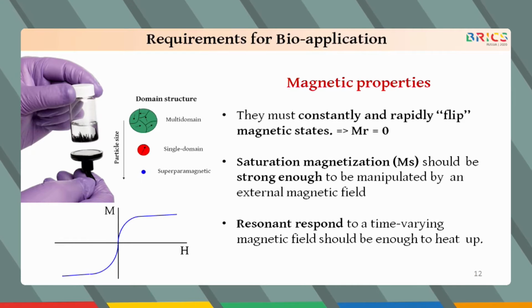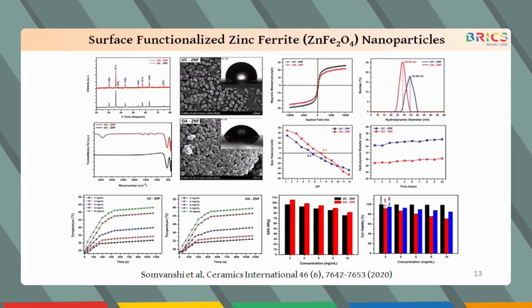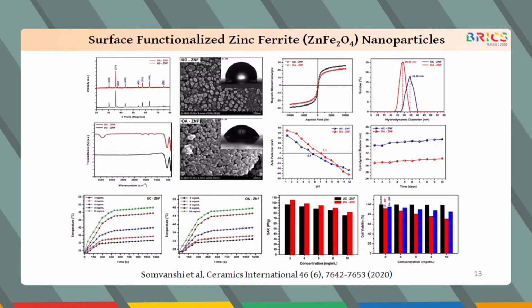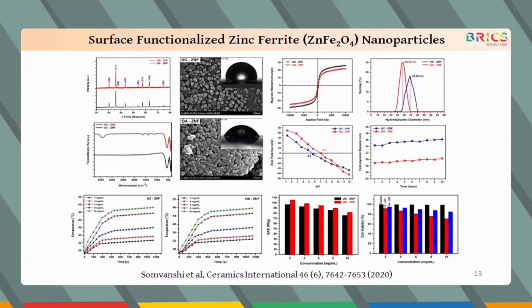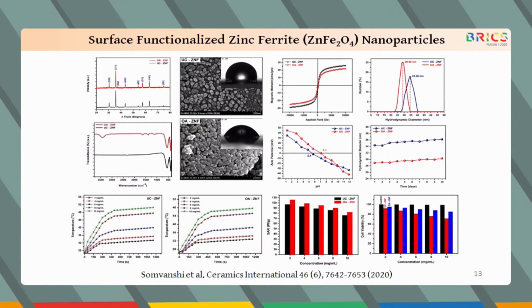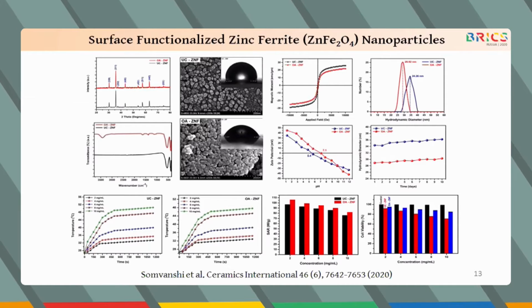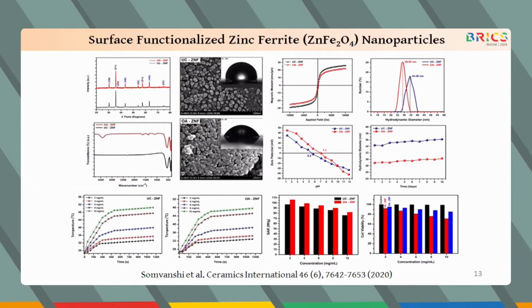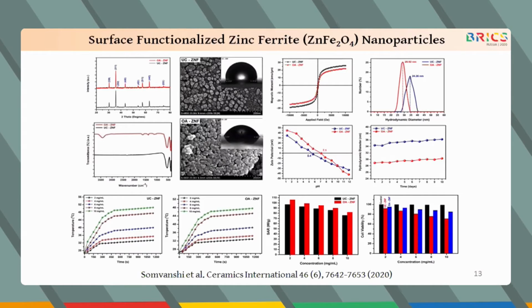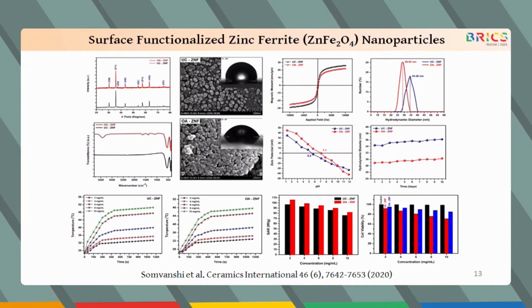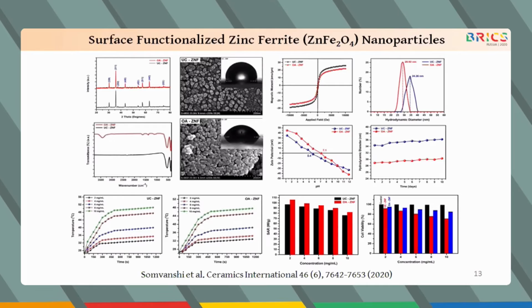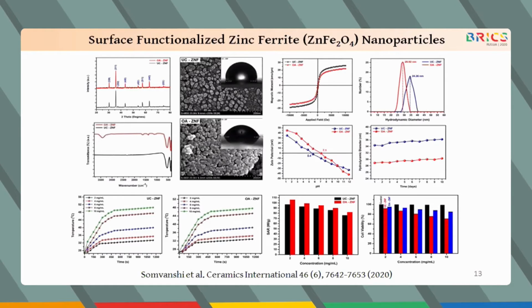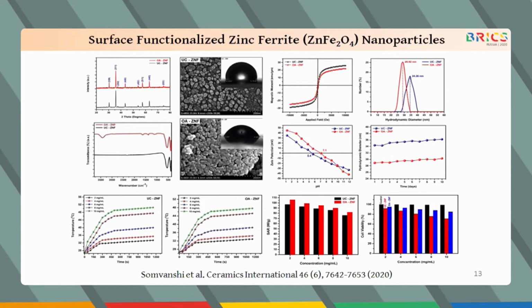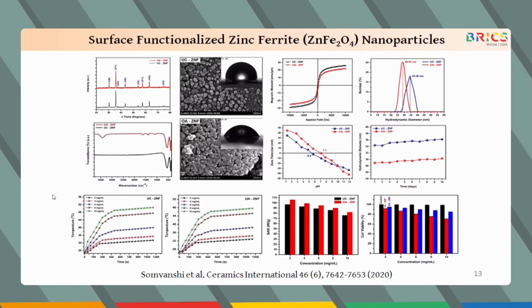So we have prepared a series of different spinel ferrite nanoparticles by a simple and cost-effective solution combustion method and functionalized the surface by oleic acid coating. You can see that XRD patterns of both the samples ensured the nanocrystalline cubic spinel lattice structure with Fd3m space group. FTIR spectra revealed the presence of vibrational frequency modes of spinel ferrites and successful coating of the oleic acid over zinc ferrite. The nano-sized spherical grains with some agglomeration of oleic acid coating over zinc ferrite nanoparticles can be visualized in FESEM images.